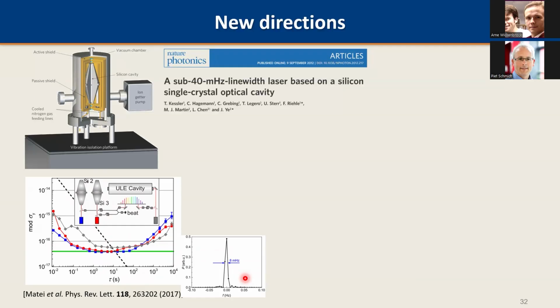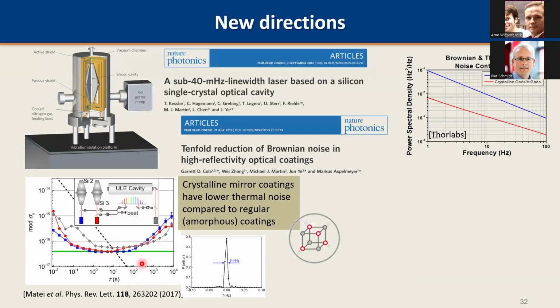The remaining problem here was that they still used amorphous coating on their mirrors, which is not a single crystal, has very low Q, and was responsible for the dominant noise. That's the green line here, essentially. That's given by the coating. Now, the next idea is, why don't we use single crystal coatings? And so they did.